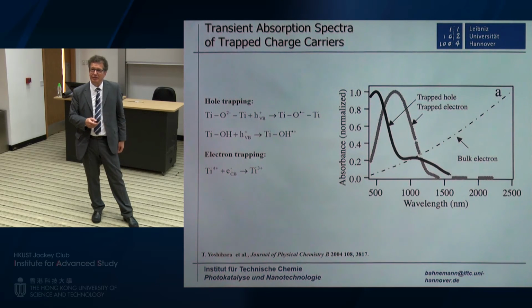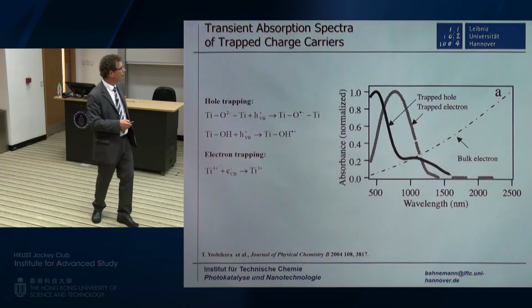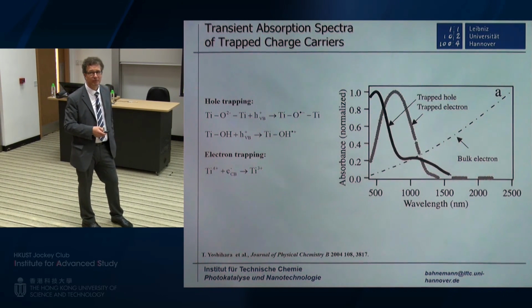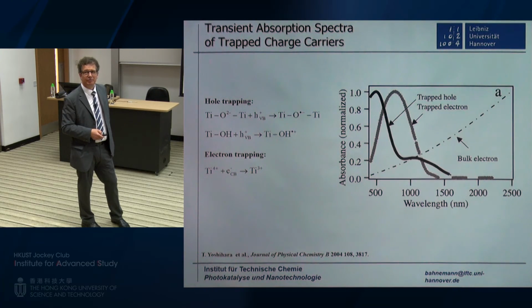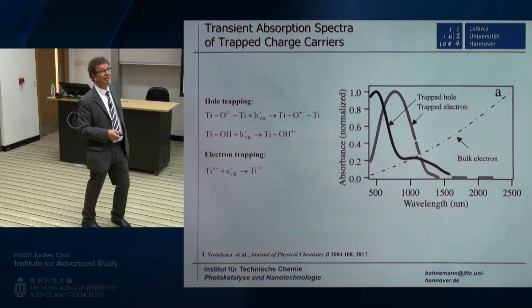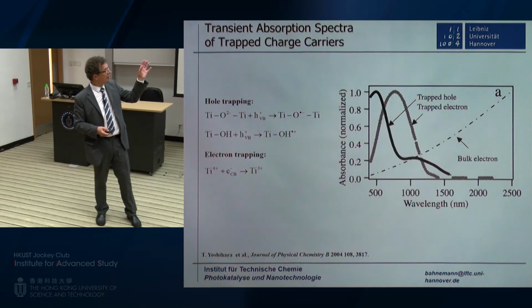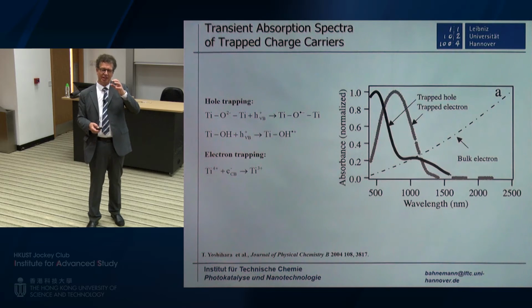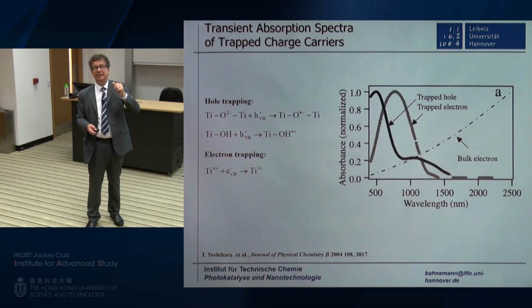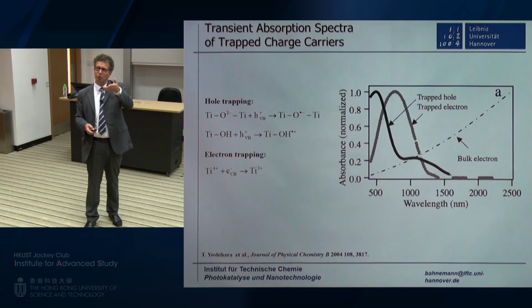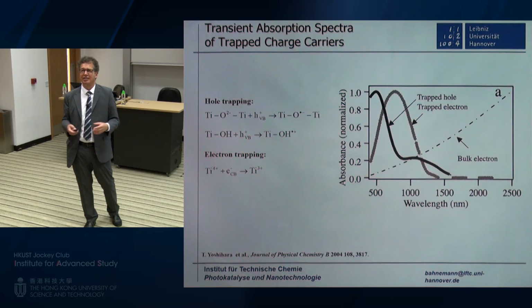So in your case, it means that the electrons you do not observe are neither trapped in the titanium nor in the bulk electron reservoir, something like this. Mm-hmm. And so you previously showed that there are some deposits of small nanoparticles on the surface of titanium oxide. Do you have this kind of thing in this system? You mean in the system when we have... okay. Yes, we also did these experiments when we had platinum or silver or something like that on the surface. And if we do this, then we see an increase of the signal of the trapped holes, and the electrons are then only trapped at these noble metal sites, and there they don't show any transient absorption. Yes, we have done this, and this increases the absorption of the trapped holes.